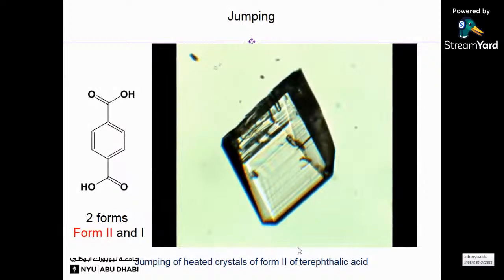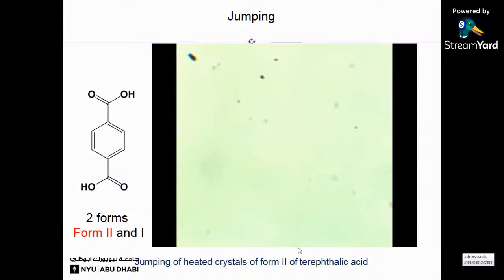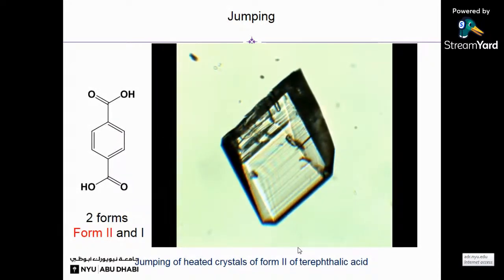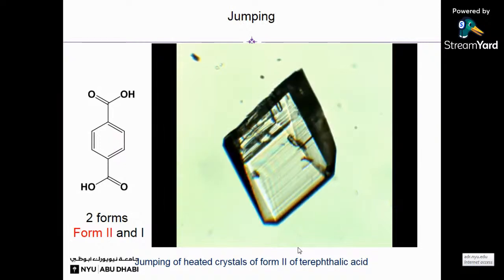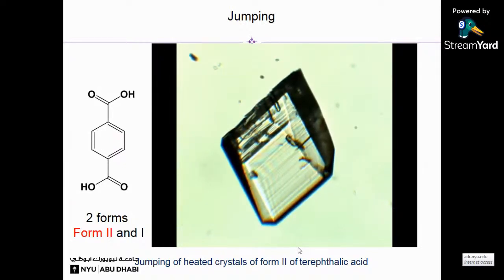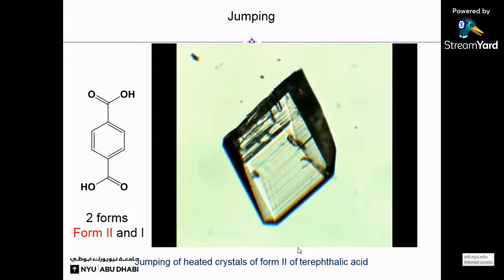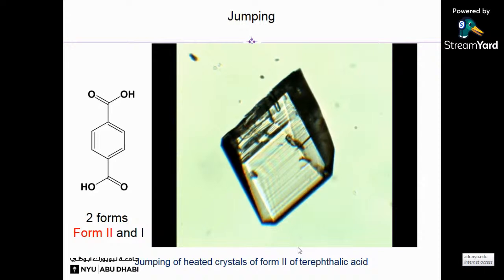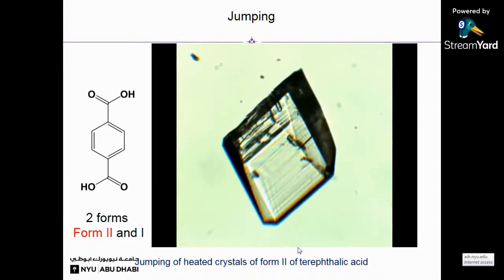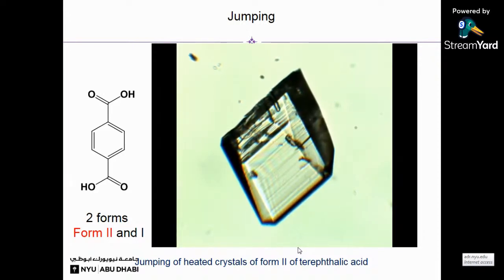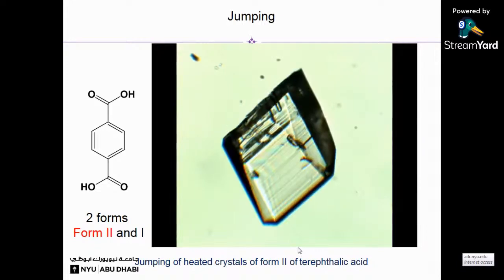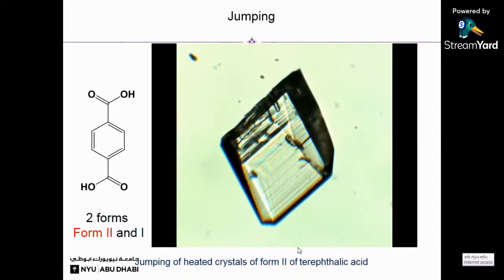So this is a simple molecule known as terephthalic acid. It can be crystallized into two different polymorphs, form 1 and form 2. Form 1 does not show any kind of behavior, but form 2 has very interesting properties. When you take these form 2 crystals and heat them just above 70 degrees centigrade, they actually jump. As you can see here in the video, the crystals are jumping.